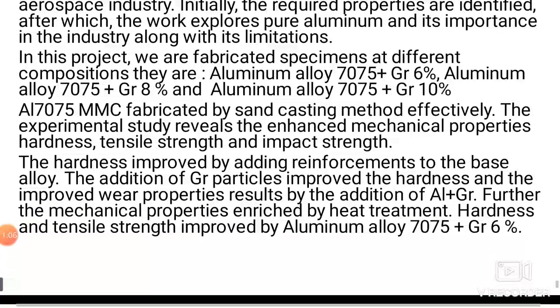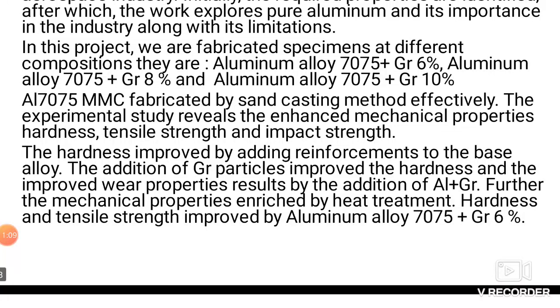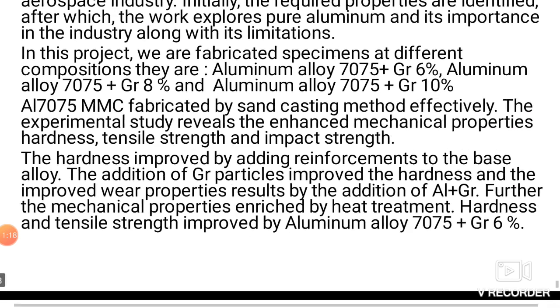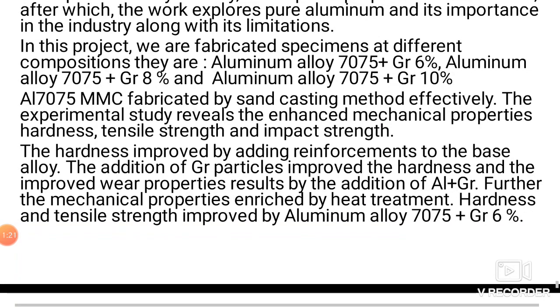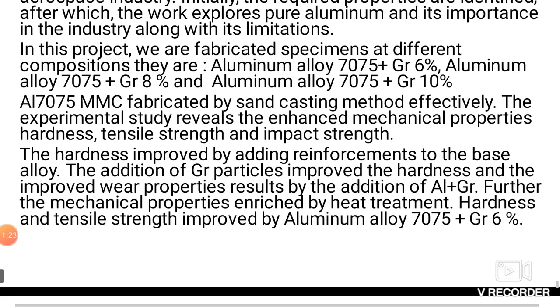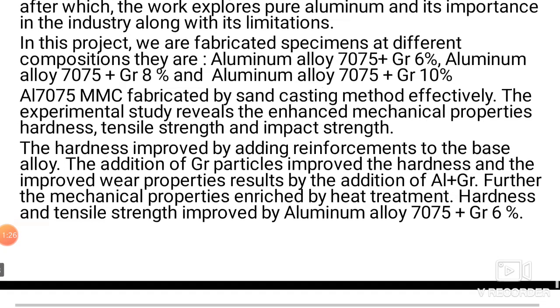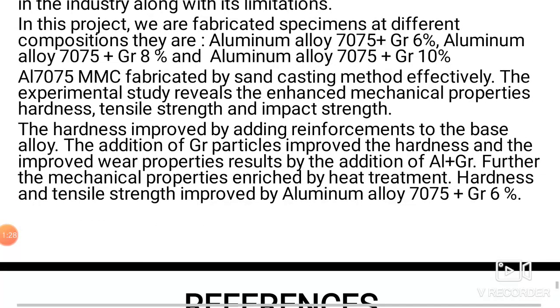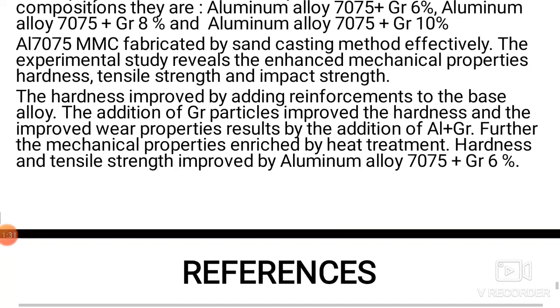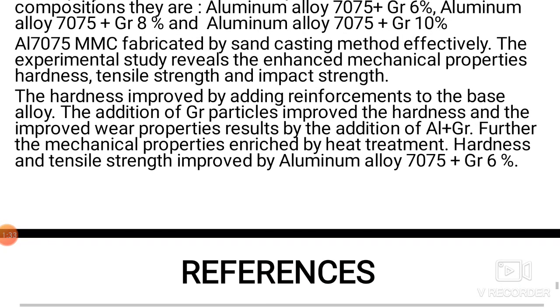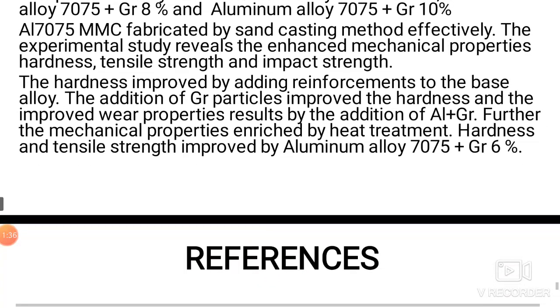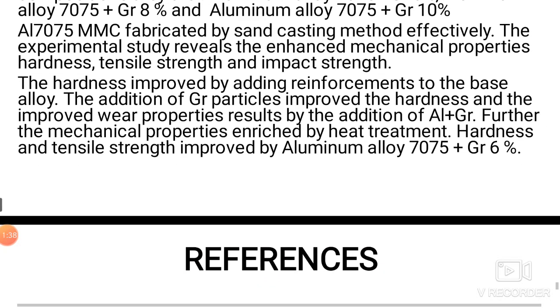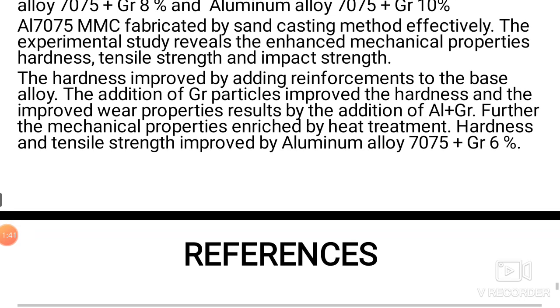These are fabricated by the sand casting method. We chose this casting method because it was simple, easy, and we saved money. It reveals that the casting procedure has enhanced mechanical properties: hardness, tensile strength, and impact strength. The hardness improved by adding reinforcement to the base alloy. The addition of graphite particles improved the hardness and wear properties as a result of the addition of aluminum and graphite.